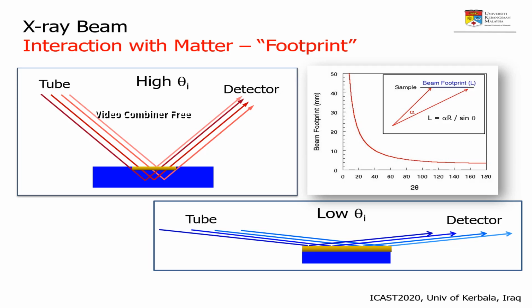Thus, the detected reflection signals not only carry information from the film, but also include the information from the support, as schematically shown in the top left image. In the worst scenario, the detected signal from the thin film is so weak that almost 100% of the reflected X-rays carry the information of the support.